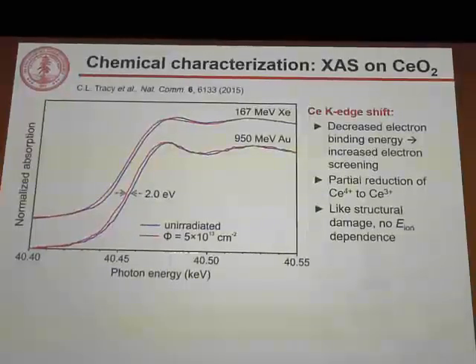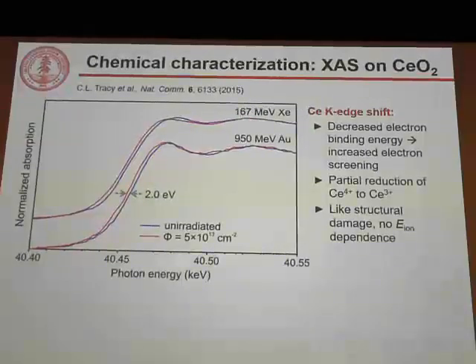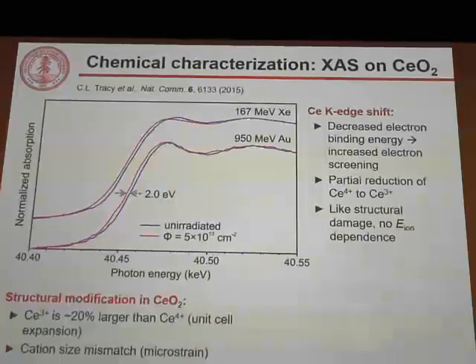Like structural damage, we don't see any dependence of this chemical change on the ion energy. Comparing the 167 MeV xenon and the 950 MeV gold, we see about a 2 eV shift in both cases. And we know, in fact, that the structural modifications we observe can be caused specifically and only by this redox effect, because trivalent cerium is about 20% larger than tetravalent cerium, so that can cause expansion of the unit cell, as we observed. We also know that if we're reducing only some of the cerium, we'll have a mismatch in the cation size between the trivalent and tetravalent cations, which will cause the heterogeneous microstrain that we've observed.